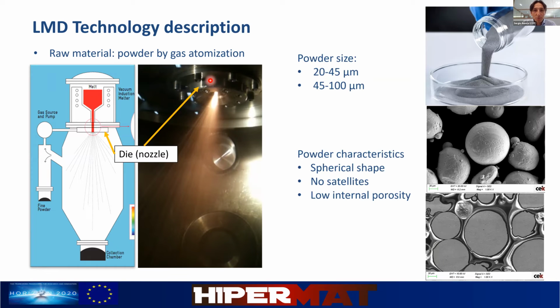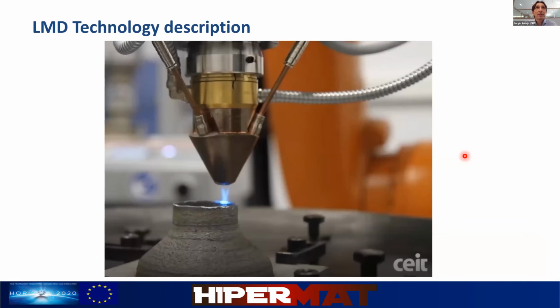The powder size used for LMD technology is usually between 20 to 45 microns or 45 to 100 microns, depending on the equipment you are using. Ideally, the powder should be spherical with low internal porosity. You can see in this picture that the porosity is very, very small, and there are no satellites. Satellites are these small spheres attached to the bigger ones, and the powder flows better with no satellites. So that's the reason to prefer no satellites.